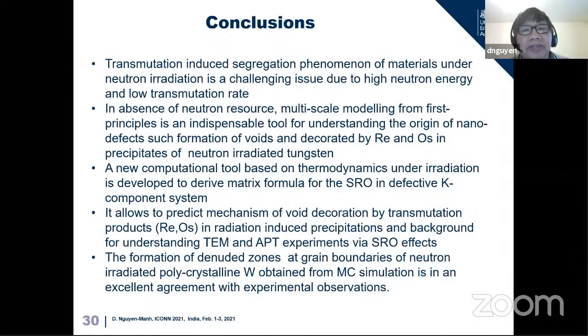So the conclusion, the takeaway message of my presentation, is that transmutation is producing new elements in the material, and it is causing many problems for material under neutron irradiation because it is changing the composition. In the absence of neutron resources, multiscale modeling from first principles is really important for understanding the origin of nano defect formation, such as voids decorated by rhenium and osmium. The new computational tool allows us to predict inside the nano defect the correlation between different solute elements in terms of short-range order, and we are also able to compare with experimental data.